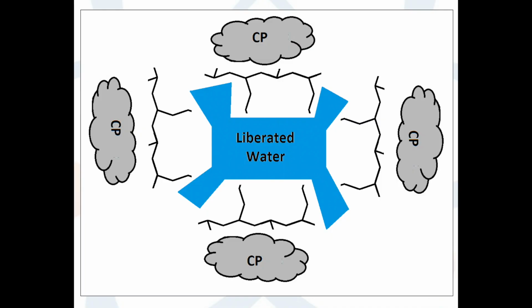And this is what it's doing. Now granted, this is a rudimentary, not to scale drawing, so the polycarboxylate comb polymers are not actually this big. One does not cover the entire cement particle. You're actually going to need a lot in a localized area to cause that deflocculation. But as you see, they're going to get in between each other. They're going to attach onto the cement particle surface, and those external teeth are going to push each other away to cause that deflocculation. And all of that is based on the cementitious chemistry.